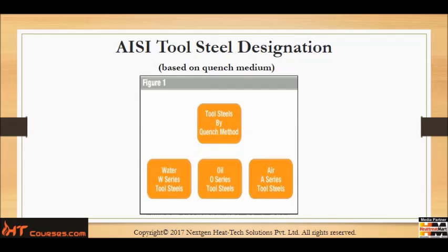And the significance about these tool steels is that once you have austenitized the tool steel, taken it from the furnace, sat it down in a draft-free environment, or you could put an air blower onto the material and blow it cold, and you will find hardness values up to 55 to 62 Rockwell C scale.